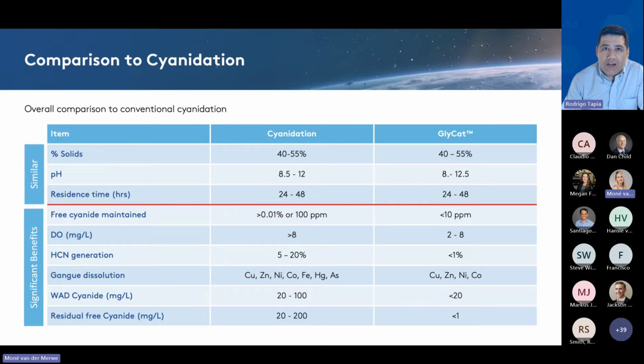For instance, Glycat requires significantly less cyanide, just 10 ppm compared to 100 ppm in traditional cyanidation. It also needs less dissolved oxygen, since Glycat reactions themselves act as oxidants. This minimizes oxygen consumption and reduces the risk of hydrogen cyanide release if pH levels drop. The gangue dissolution is significantly less with Glycat due to its selective nature. This minimized dissolution indicates a more efficient process from a metallurgical recovery standpoint.